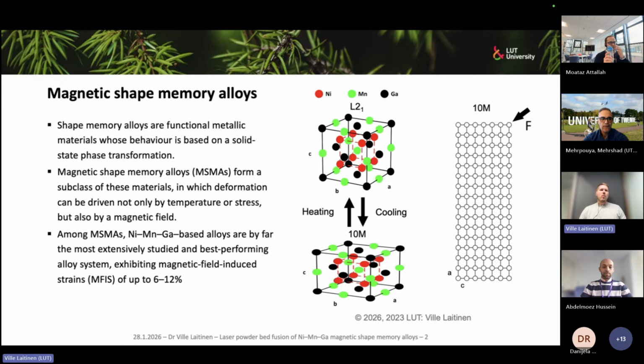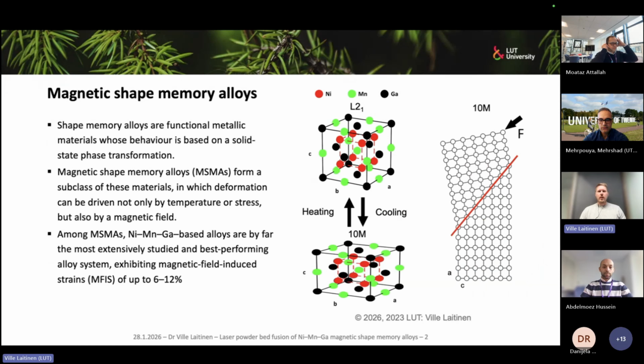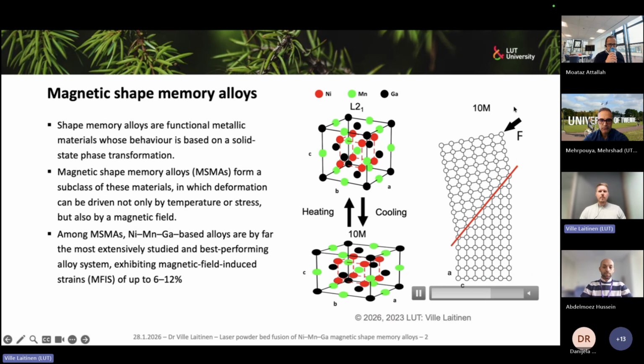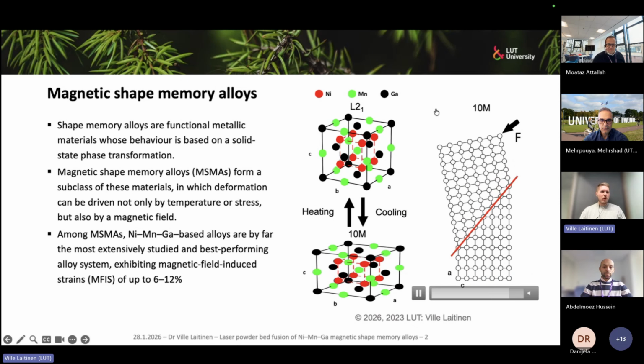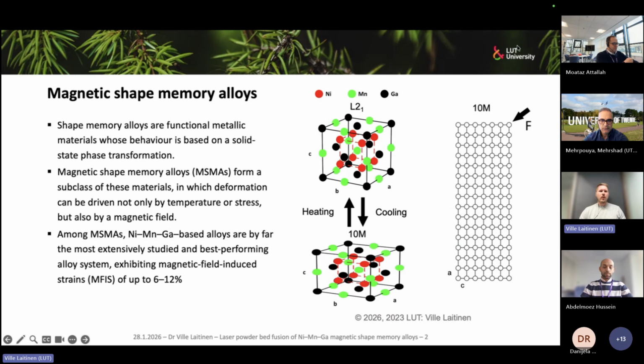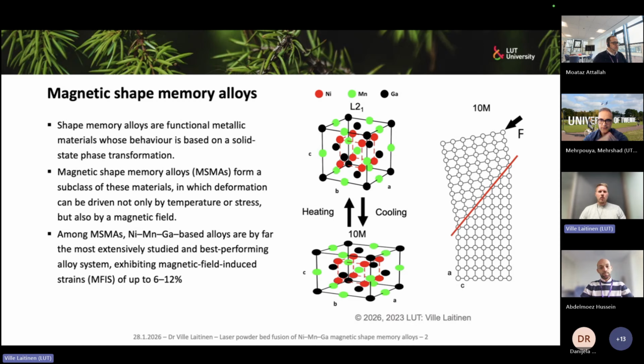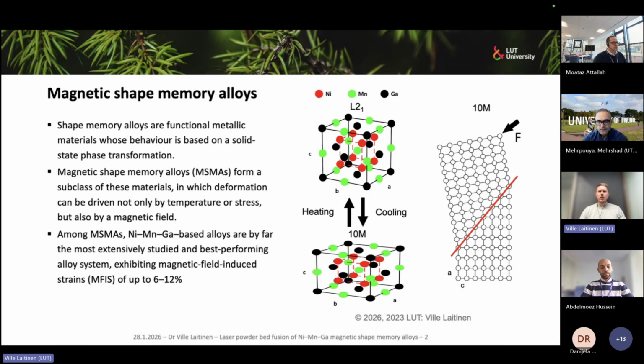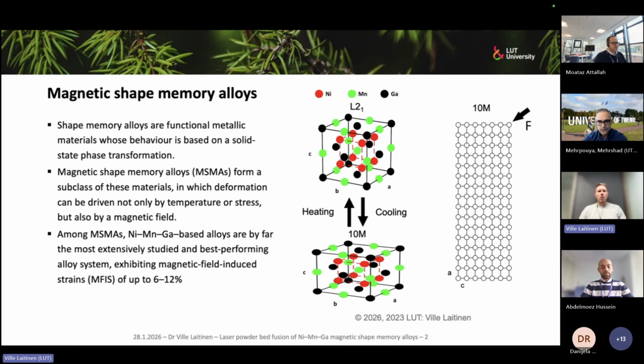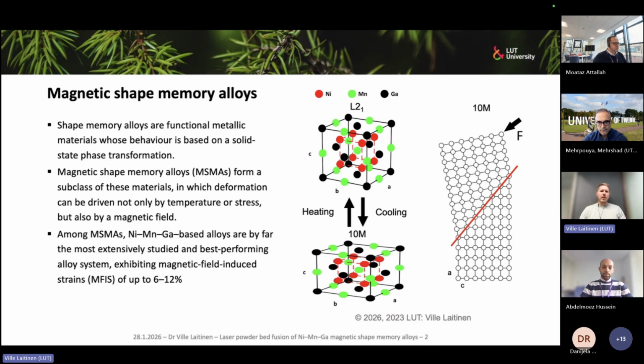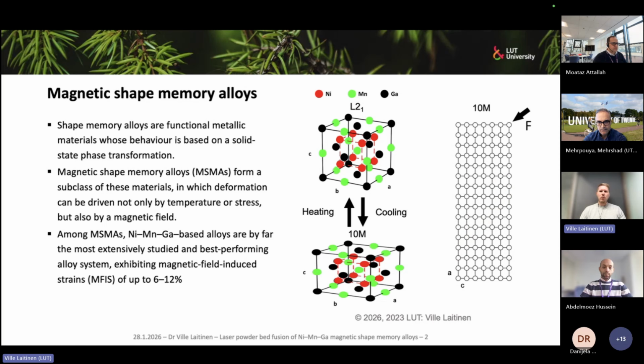So, a little bit of background. What do we mean by magnetic shape memory alloys? First, we have conventional shape memory alloys, which have the shape memory effect and superelasticity based on low temperature martensite, and especially its ability to form martensitic twins. The core phenomenon in martensite is that through twinning, it can dissipate a lot of shear forces in a manner that provides a plastic deformation, but a deformation that is fully reversible.